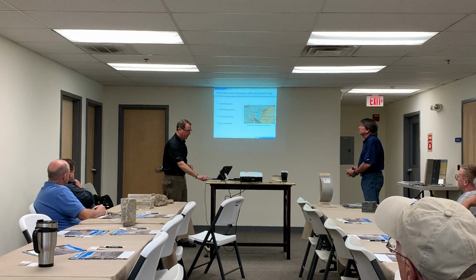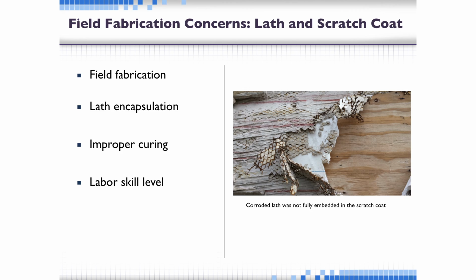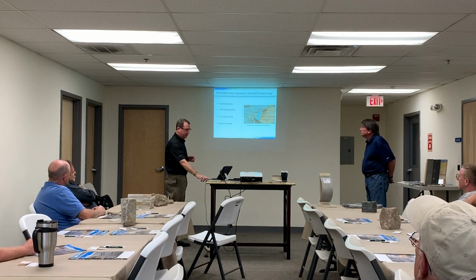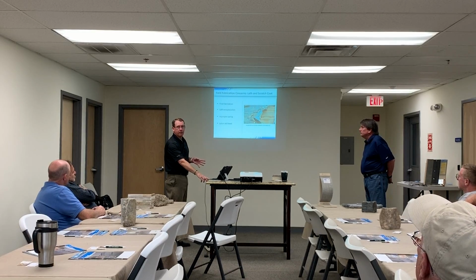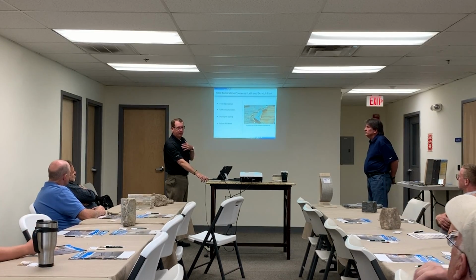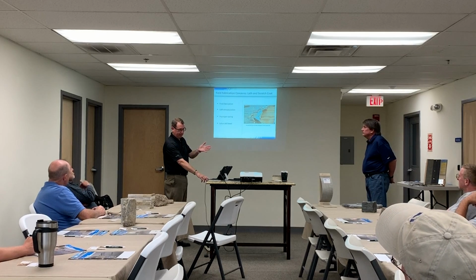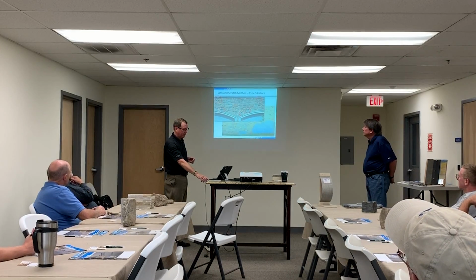All right. What we try to prevent is this. So if lath is not properly encapsulated, or something happened in the rain and they're working in the rain, whatever it is, we can get rust and nothing can stick to rust, right? So that caused a lot of the pops over time. Water got back there, it can freeze, and then it will pop a stone. So we've got to make sure that that's fully cured. It's not an issue with the cement board because it's already made. It comes on a tractor trailer truck, and it's delivered, and you start hanging it as soon as it shows up.